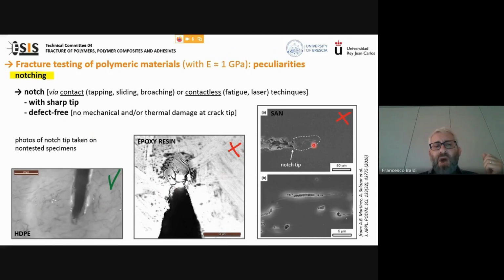Now, if you look at these photos of notches taken on non-tested specimens, we can observe that this picture on the left refers to a high-density polyethylene. In this picture, I have no damage. I cannot see any damage in front of the tip of the notch. Whereas in the other two photos that refer to an epoxy resin and to a styrene acrylonitrile polymer, I can observe some damage of the crack tip. Here on the right, for example, there is evident plastic deformation that was introduced during notching. We have to avoid this situation.